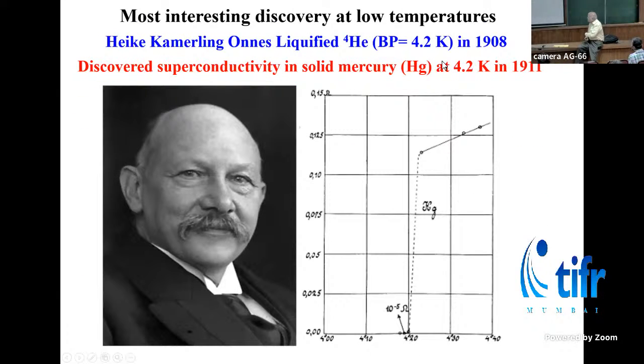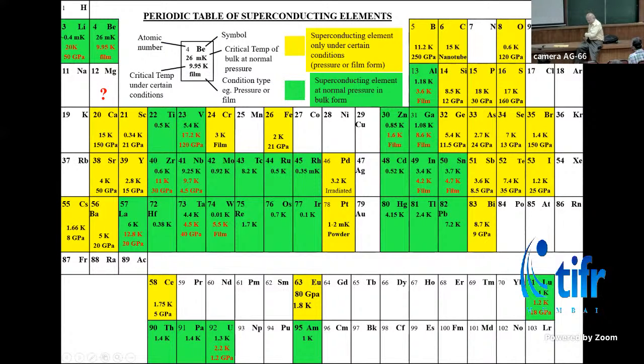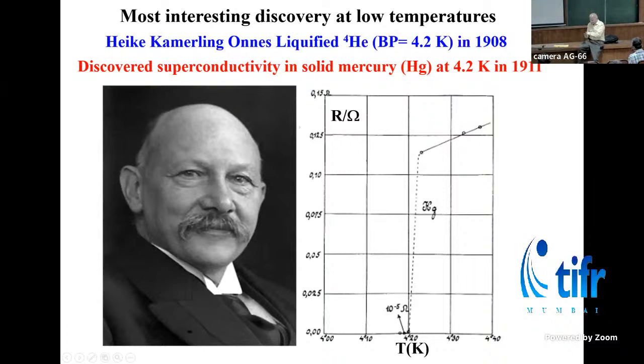So we go back to Kamerlingh Onnes, because any superconductivity talk cannot be without his photo. Everybody shows this very nice resistivity data, but nobody realizes how the measurements are made. He is talking about 125 milliohms there, going down to 0. This is the resistance of mercury. Right now the best samples have a residual resistivity ratio of 1000, and for him at that time it must have been at least 100, which means 12.5 ohms at room temperature. To get 1 ohm of mercury resistance, you need 1 meter of mercury in a 1 square millimeter cross section. Imagine how much struggle he went through to have 12.5 ohms, and it goes to 125 milliohms, then he sees it go to zero. It's a marvel.